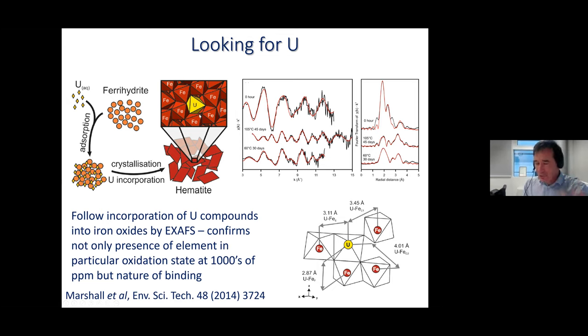Now, if you try to perform a diffraction experiment of that, you wouldn't see the uranium in the structure because it's not directly part of the crystal structure. It's part of the crystal structure, but it's there as an impurity in a relatively low concentration. So what the experimentalists want to do is to understand how and where the uranium was bound up in the crystal structure, and also the extent to which that depended on the nature of the chemical processing. And XAFS gave them a probe that was specific. It was tuned to the uranium, and it gave them information about what the local distribution of atoms was